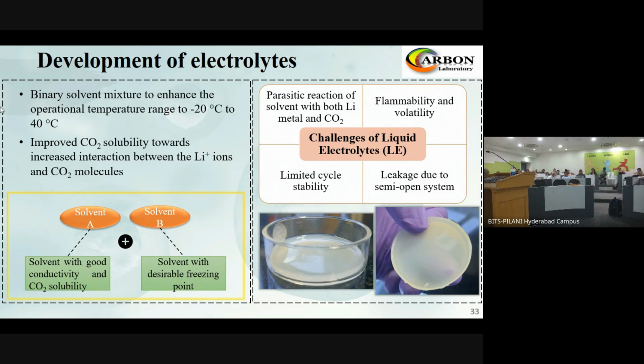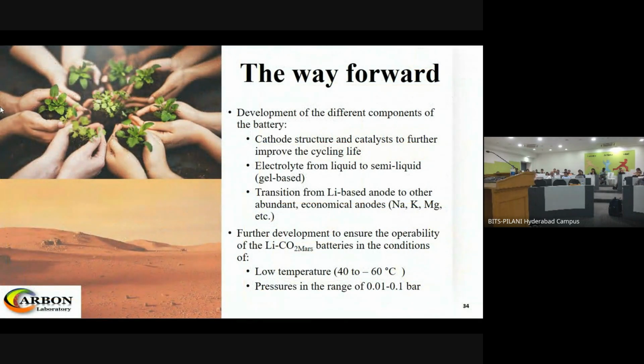Of course, we have achieved till now around 200 cycles in the latest work, but if we compare it with commercial lithium-ion batteries, we need to go towards a minimum of 1,000 cycles. So there is a long way to go. So the way forward for us, we are looking into the different components. Today I just presented the cathode part. So cathode is structure and catalyst to further improve the cycling life. Electrolyte from liquid to semi-solid, semi-liquid or solid. Then again from lithium-based anode to other economical and abundant ones like sodium, potassium, magnesium and multivalent electrodes.